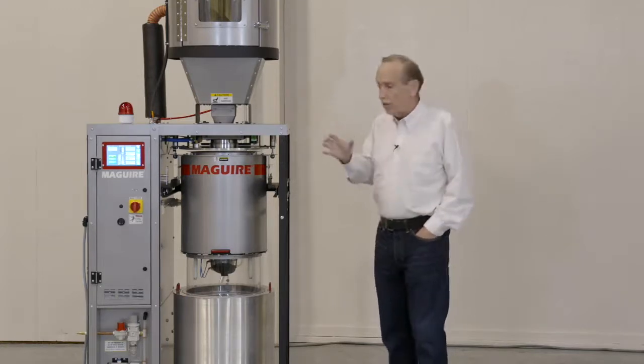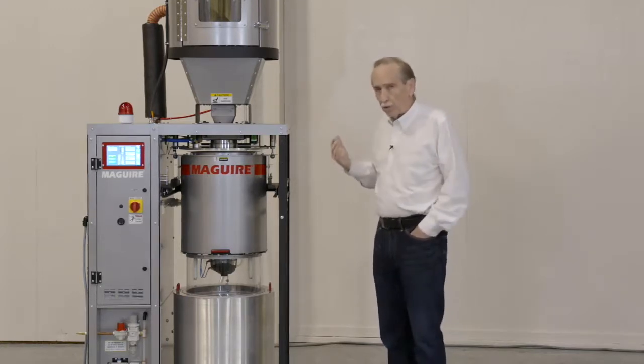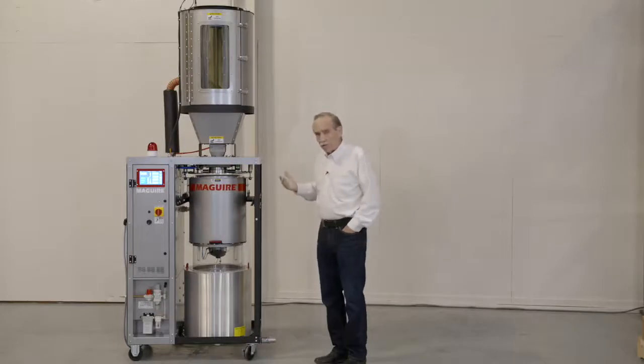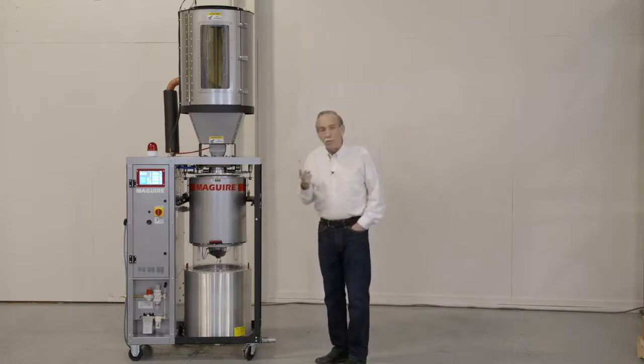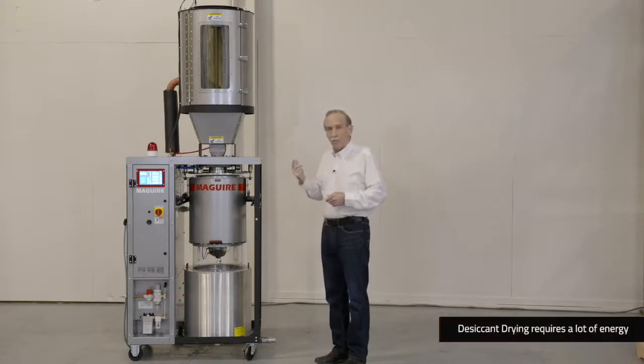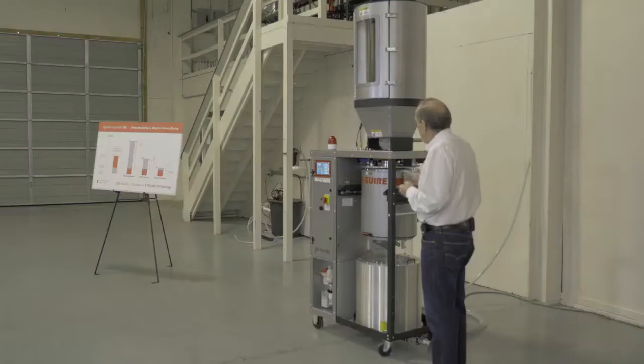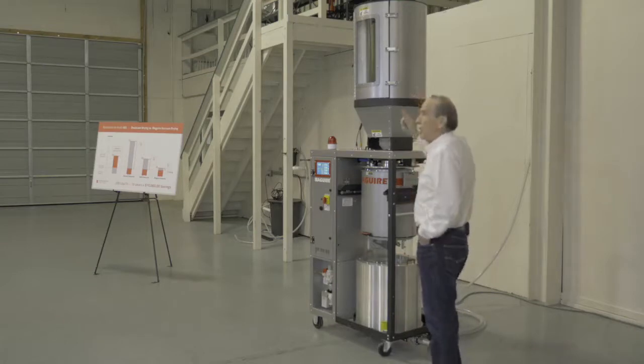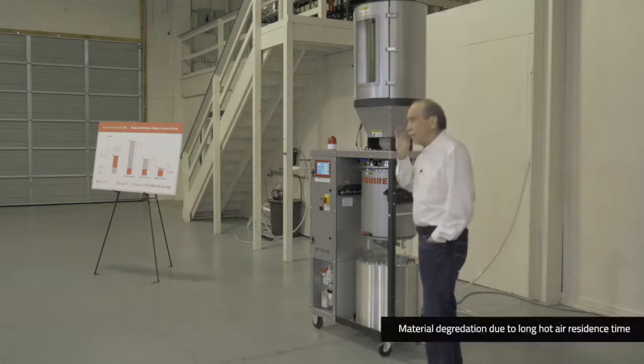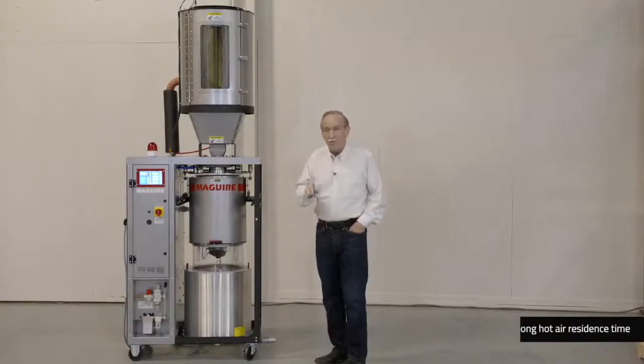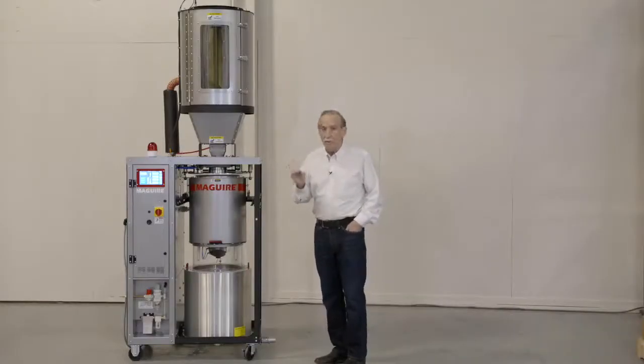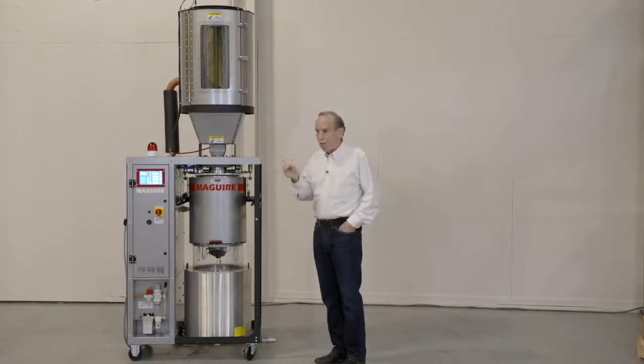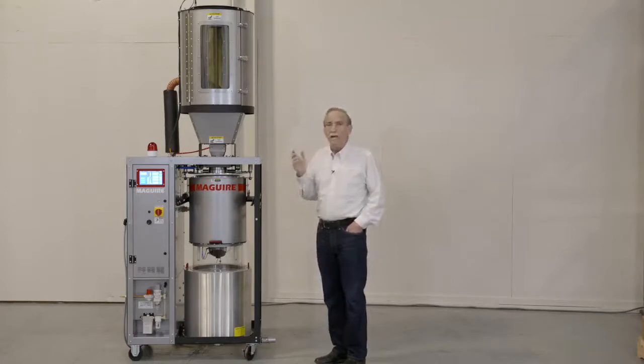And in some dryers, larger ones, you may even cool the air with a cooling circuit so that you can get more moisture out of it while it's cool, and then reheat it again and go through it again. Well, there's two big problems with that. You're heating and cooling, heating and cooling, heating and cooling. So you're using a lot of energy. And the recirculation is degrading, to some extent, the plastic. Now, that's not true of all plastics, but in some cases, in some plastics, it's very true. Nylon, PET, polycarbonate, they all would prefer not to be heated for 4 hours before they're processed.